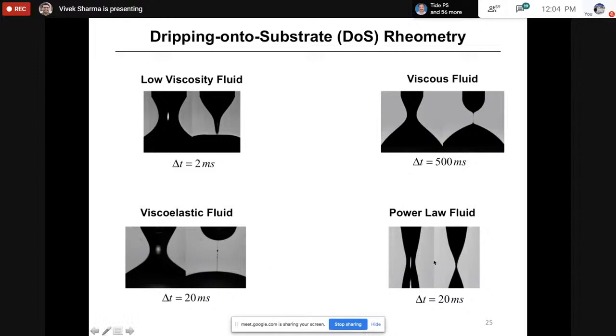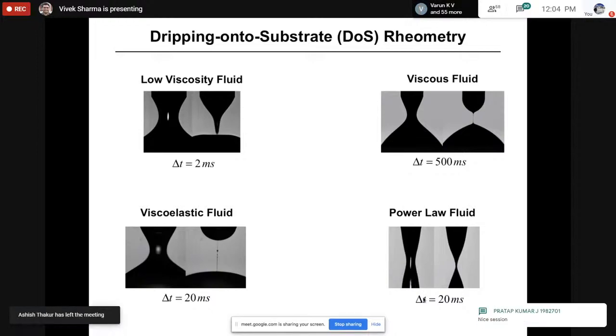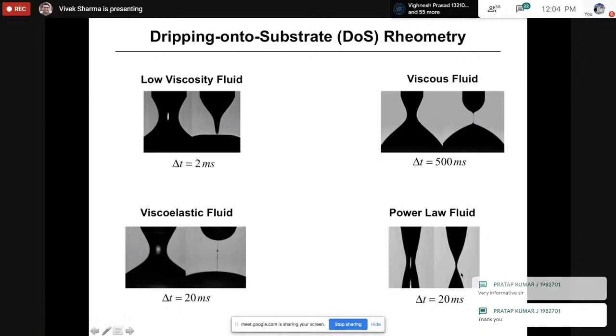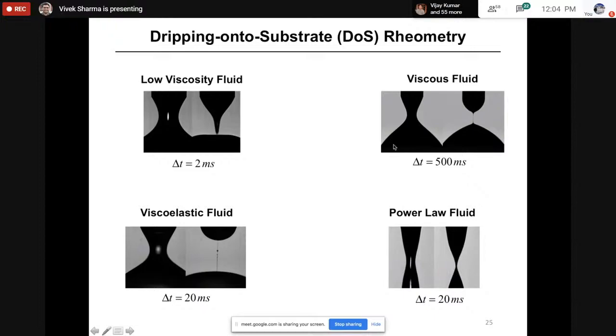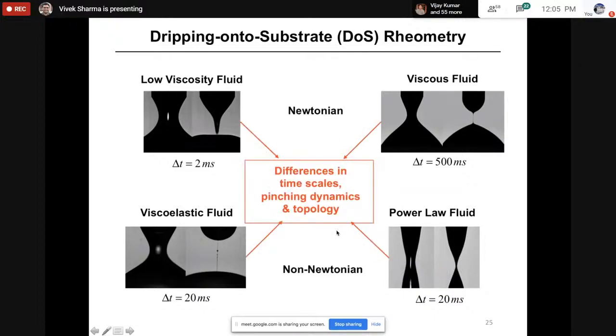Lastly, many non-Newtonian fluids, many power law fluids, many formulations that have more than just polymer in them, have other ingredients in them. These shear thinning systems tend to behave like power law fluids in terms of shear rheology, and also in radius evolution, they show power laws. But in terms of neck shape, you can see formation of these two cones. So there are very distinct time scales, very distinct pinching dynamics and topology.